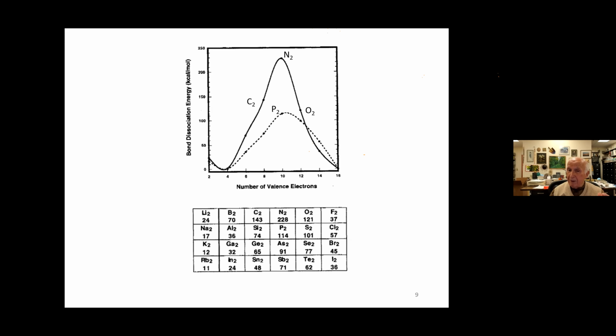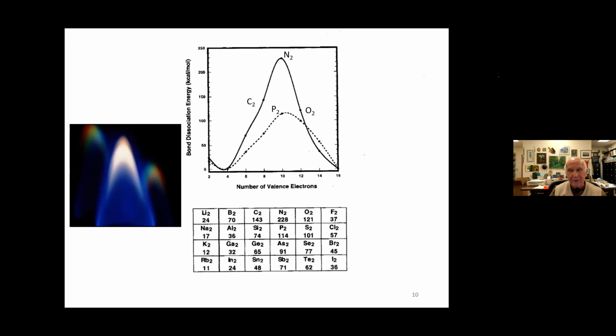So they are stable, but you haven't seen any bottles of C2 or P2. And you will never see a bottle of C2 or P2 because they are spontaneously polymerizing. We actually see C2, the blue color in hydrocarbon flames is due to an excited state of C2 emitting. But the diatomic molecules, even though they are stable by 5 eV to breaking apart, that's what it takes to break them apart, they are, in fact, very reactive. So just because you are stable does not mean that you're not reactive. That's the other lesson of chemistry.